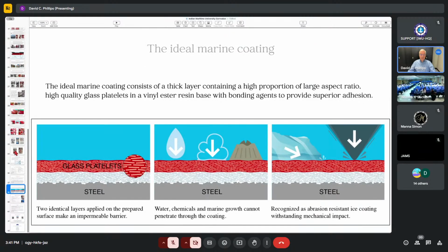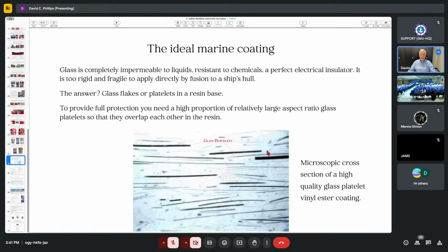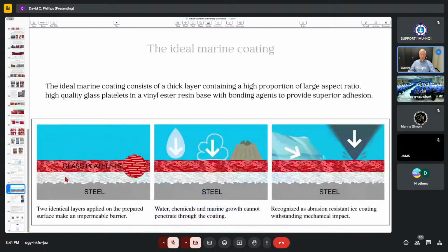So that's the coating. That's what it is. It's high aspect ratio, special glass platelets in vinyl ester with bonding agents to make it stick. It's 1 millimeter to 1.5 millimeters thick, which is thicker than most coatings go on. The epoxy is usually applied at about 500, half of that. So it's thick, you're putting more paint on, and it's designed to last 25, 40 years, the life of the vessel.